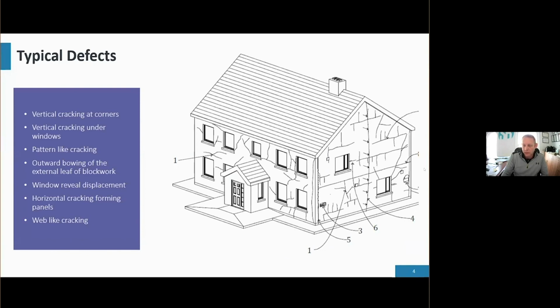I hope everyone can see my cursor on the screen, but just looking down, we've got vertical cracking at the corners, a very typical signal of damage from pyrite. Cracking under windows, and again, I'm not telling you something you don't already know, particularly homeowners. The pattern-like cracking that we can see at various locations on the gable shown here, the outward bowing, which is typically shown vertically and horizontally along the center lines. Displacement around the window and door reveals, that's another common element of damage.